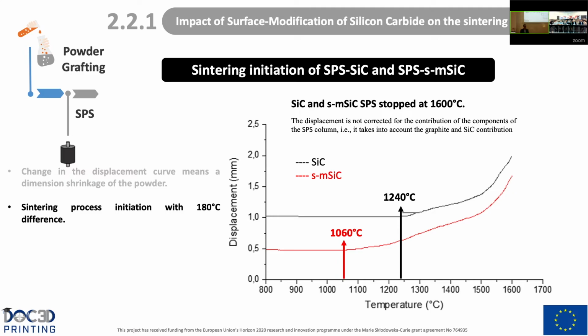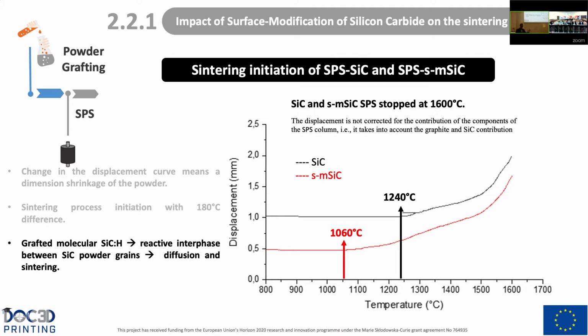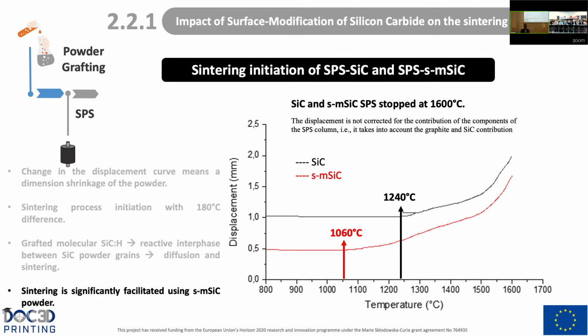But why? What is happening here? Actually, the grafted molecular silicon carbide hydrogen is forming a reactive interface between silicon carbide powder and actually it's facilitating the functionalized system. So finally, the sintering is typically facilitated using surface modified silicon carbide powder instead of non-functionalized silicon carbide.